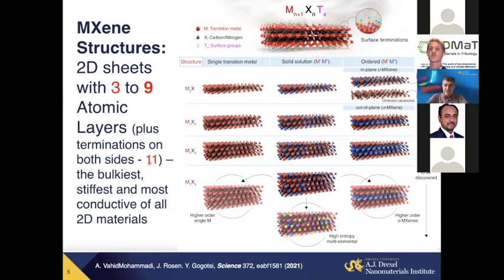One of the interesting things to mention is that MXenes are making not only more or less regular, very thin, few-angstrom structures, but also the thickest known, a bit larger than 1 nanometer, with 11 layers if you count surface terminations. And what it gives them actually is rigidity. They are much stiffer. The bending modulus is a couple of orders of magnitude higher compared to thin materials like graphene.